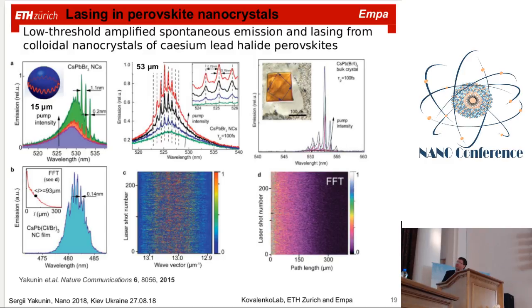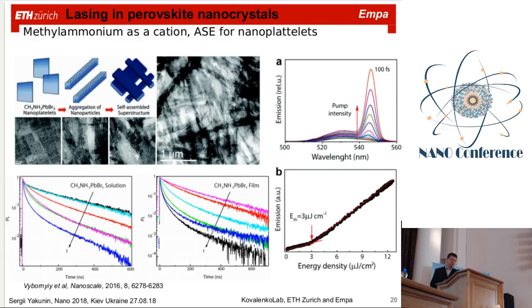This lasing effect is also known as random lasing, where in a single-shot spectrum you see chaotic positioning of sharp lasing lines. They do not repeat, so with any new pump shot they show a quite different mode structure. This is a very modern direction where people expect a bright future of this application for security and cryptography. But we are mostly a group oriented on chemistry. That's why we have a lot of people providing different materials, and we were really interested in playing with different chemical compositions and different morphologies of perovskites.